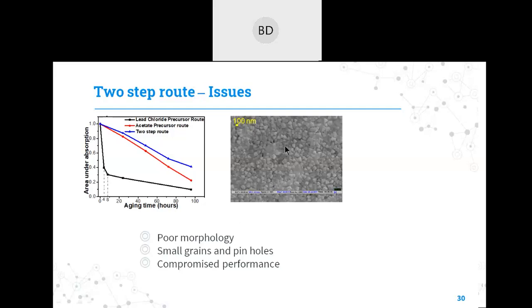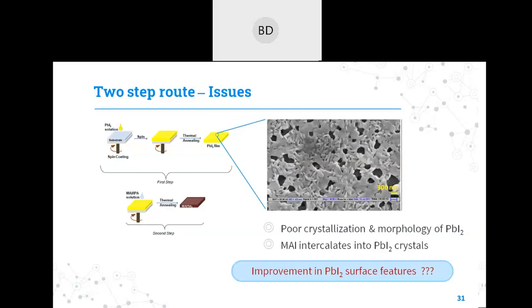But if the grain sizes are smaller and there are pinholes, then there will be some shunting path provided in the perovskite film, and it will lead to degradation and a decrease in the performance of the perovskite. So what we did is we tried to further improve the two-step performance as well as the stability of the two-step route.